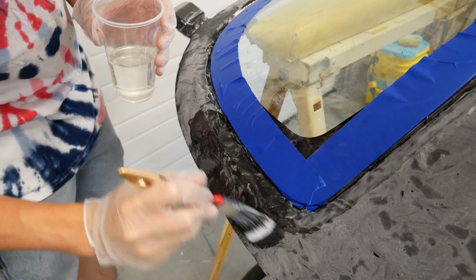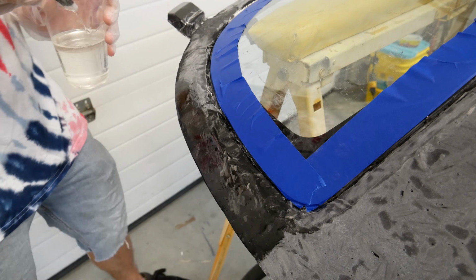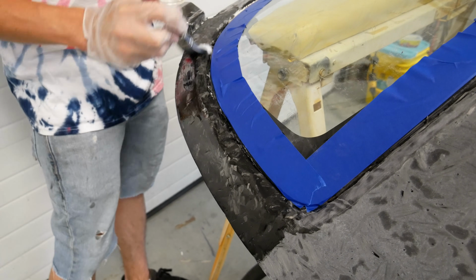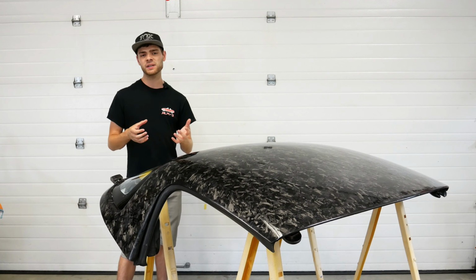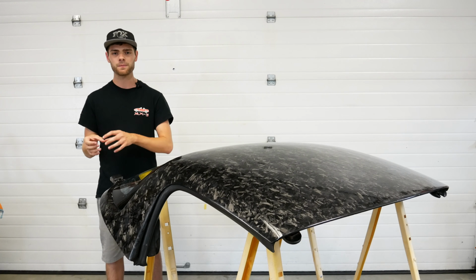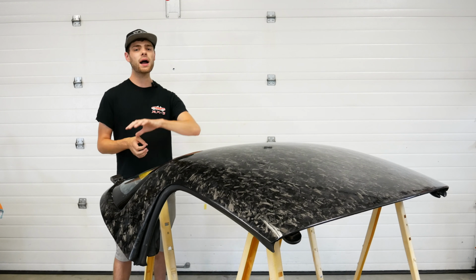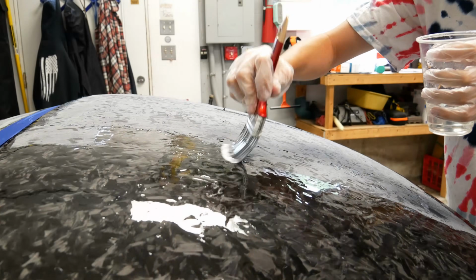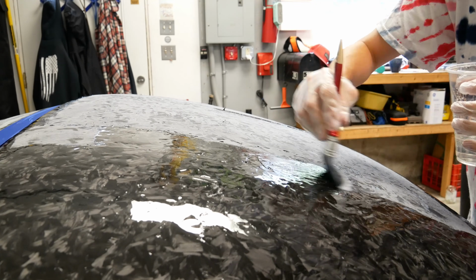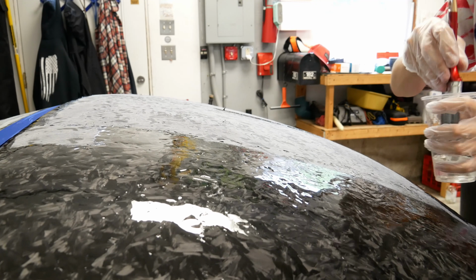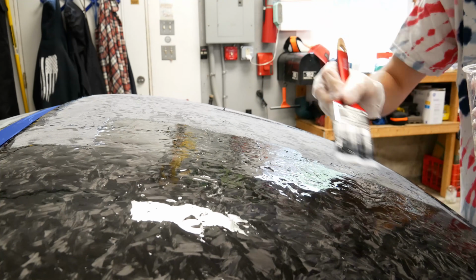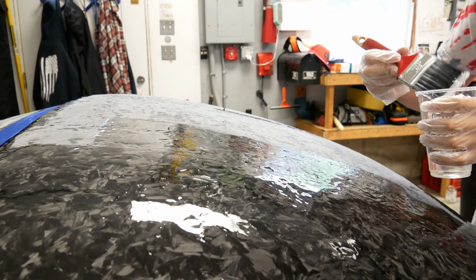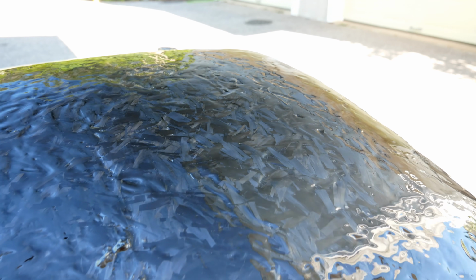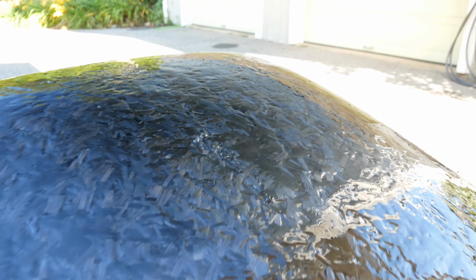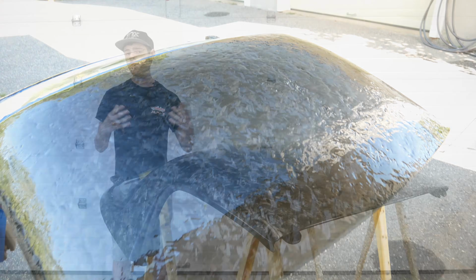In some cases, you might want to go ahead and do another layer of carbon fiber, but I didn't feel like that was necessary since I got really good coverage in my first coat. With this next resin coat, I went ahead and did the same exact process as putting the first layer down before the carbon on the top. At this point, after the second coat, the top looked really good in the sun, but once you really looked closely, you could see that that resin layer really wasn't flat and needed to be sanded down again. So that's what I did.